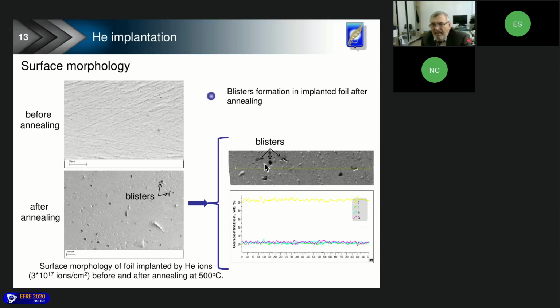500 degrees is a temperature that is lower than the crystallization temperature of the foil. At this temperature, we also do not see any redistribution of elements at the surface. Formation of blisters after annealing is generally indirect evidence of helium presence in the surface layer.